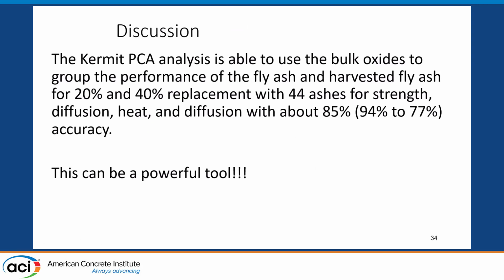So this Kermit PCA or kernel PCA analysis is able to use its bulk oxides to group the performance of the fly ash. It looks into classification. Is it better? Is it about the same? Or is it worse? 20% replacement and also 40% replacement for 44 different fly ashes. On average, it's accurate 85% of the time. Gets it right in one of those 3 categories. That's pretty good. And that ranges between 94 and 77%, depending on what it is you're specifically looking at.